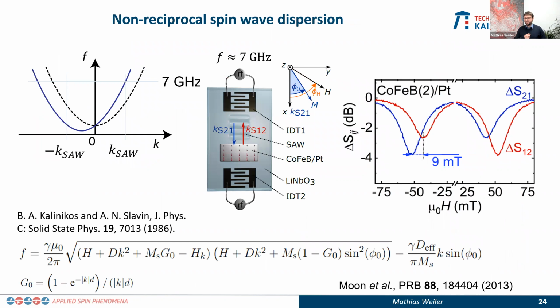So now the question is, how can we actually optimize it? And the first thing that we thought about to optimize it is, well, we can now make the system a bit more complicated by adding platinum to it, and by that making the spin wave dispersion itself already non-reciprocal. Okay, and that might help our case here.